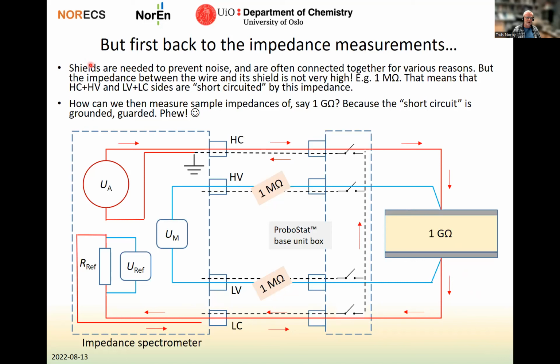But to understand that, let's go first back to the impedance measurement. Here is the impedance spectrometer again, our Solartron 1260, for instance, and all the shields and everything. And we are measuring now a very high impedance sample. So the shields are here to prevent noise and are often connected together for various reasons. Like I told you, we connect the shields together here to do the proper measurements in the Solartron. But the impedance between the wire and its shield is not very high. In fact, the impedance between the shield here and the wire here that goes inside of it is of the order of magnitude of 1 mega ohm.